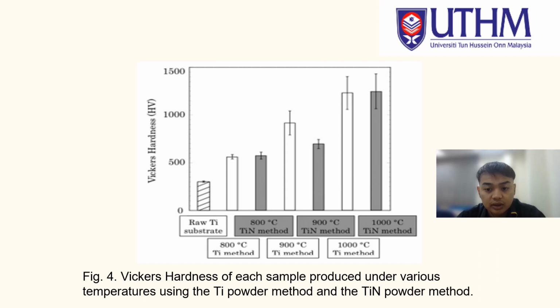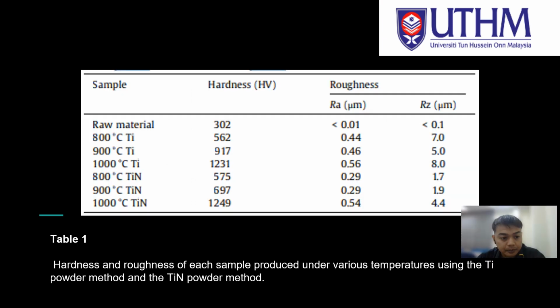Figure 4 shows the Vickers hardness of each sample produced under various temperatures using the Ti powder method and the TiN powder method. Table 1 shows the values of hardness and roughness of each sample produced under various temperatures using the Ti powder method and the TiN powder method. In table 1, Ra means arithmetic mean roughness, the absolute average relative to the base length, and Rz means maximum height of the roughness profile.